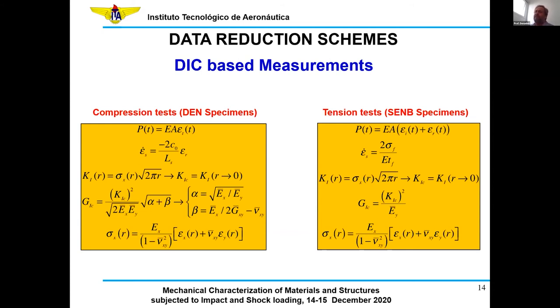And by using the DIC measurements, we can have the strain ahead of the crack tip. And knowing the stiffness of our composite, we can determine the stresses. And by using the Westergaard expression, we can compute the stress intensity factor. Of course, the targets are not quite located at the crack tip, so we don't have the stress intensity factor at the crack tip, but we can extrapolate by using the Westergaard expression the KI at the crack tip in order to have our KIC at the moment of failure.